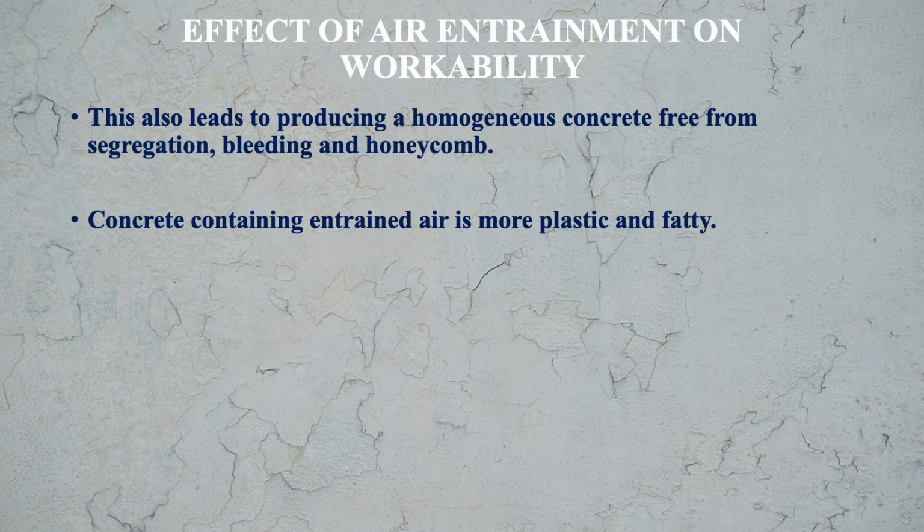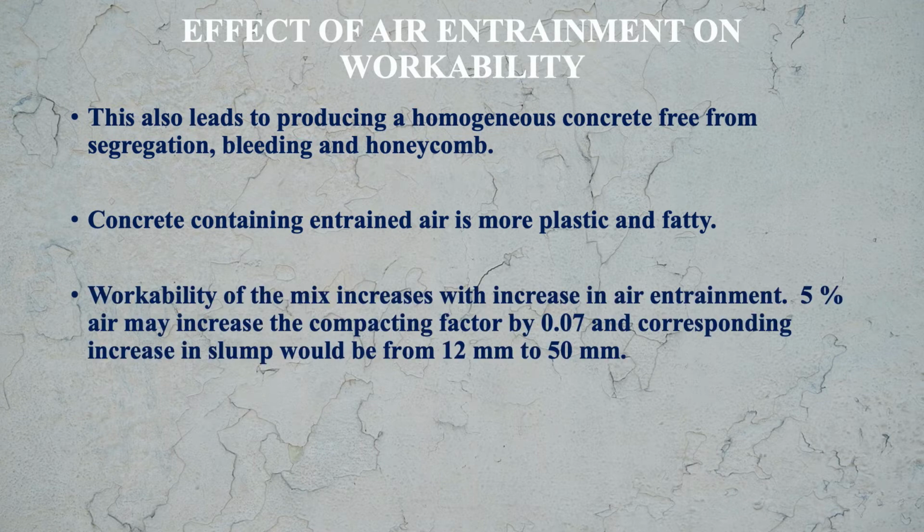Concrete containing entrained air is more plastic and fatty. Workability of the mix increases with increase in air entrainment. 5% air may increase the compacting factor by 0.07, and the corresponding increase in slump would be from 12 to 50 mm. So this is how entrained air affects the workability of concrete, and we see here how the compacting factor of the concrete increases by air entrainment, and also how the slump increases with air entrainment.